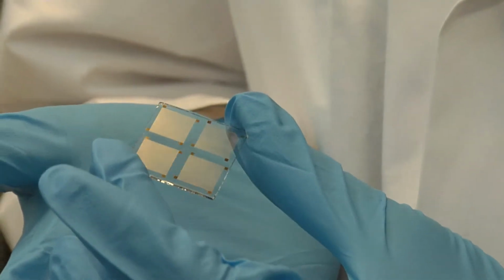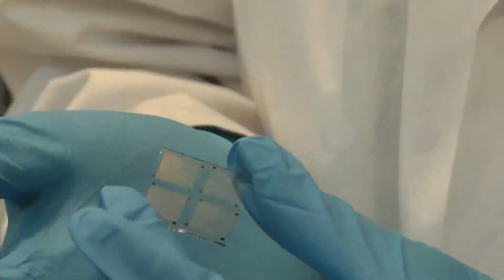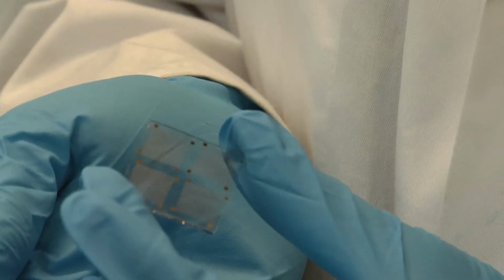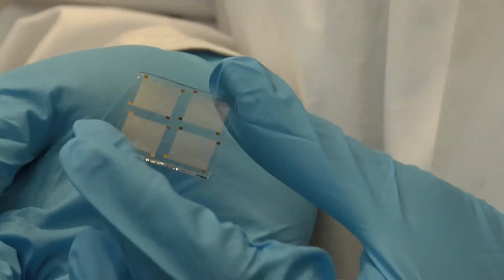And a big advantage, compared with other traditional substrates, is that the dyes on top of those substrates are just spin-coated or just physisorbed, while on the diamond surface you can make a chemical bond, enabling a better charge transfer from the dye into the diamond substrate.